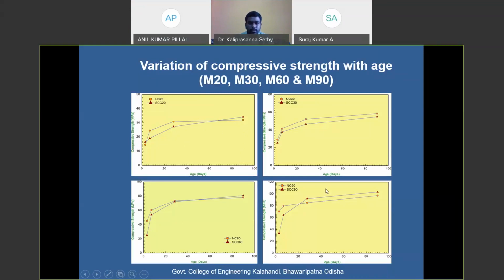So here are the results of our compressive strength, and you can see for the 20 MPa concrete at 28 days we are getting nearby 30, and at 90 days we are getting more than 30 MPa. And for all the cases you can see we are getting beyond the expectation of what we tried to design for. And for all the cases in the self-compacting concrete, at 90 days we are still getting some increment of strength, whereas there is negligible increment, or I can say no increment, at 90 days for normal concretes.